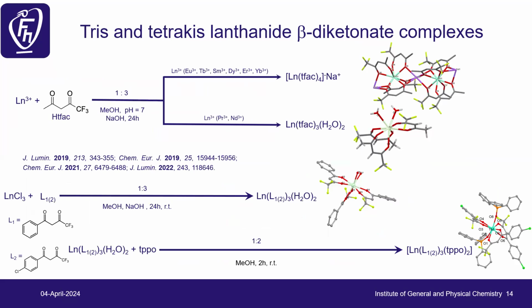In a case that I will show you here, I worked with a simple one. It's known as trifluoroacetylacetonate (Htfac), where I synthesized. What was interesting in this work was that we did it at quite neutral pH 7, so around the pKa of the beta-diketonate in this case. And when we put a 1:3 ratio for the lanthanides, small lanthanides, so because praseodymium and neodymium